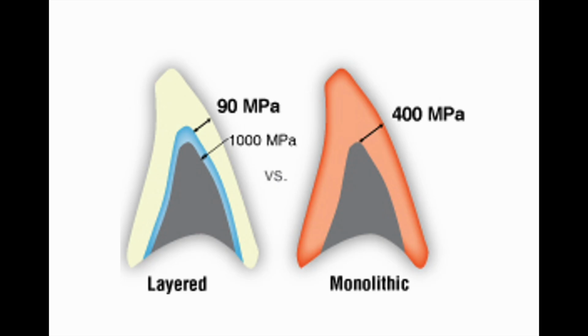On the contrary, if you compare it with a lithium disilicate monolithic crown, though it is not as strong as zirconia, it still holds an ultimate strength of around 400 MPa. That's way higher than the mere 90 MPa seen in the veneering porcelain of layered zirconia restorations. So even though lithium disilicate is technically weaker, the monolithic version of it performs far better clinically because there is no fragile veneer waiting to chip off.